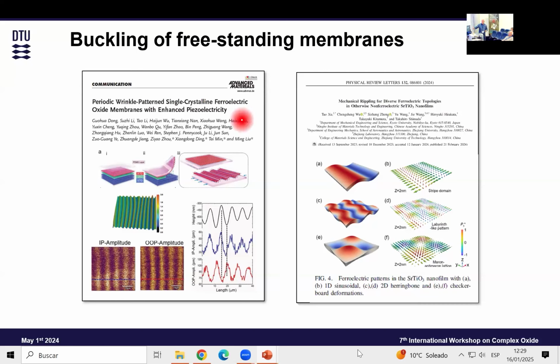So there is a response of ferroelectricity, or at least a response from the PFM, when you strain the material by forming wrinkles in the material. In another paper here, people predict some of the effects that can happen in freestanding membranes. If you have freestanding membranes with different shapes, they predict that you can induce ferroelectricity due to the flexoelectricity, basically. This is what motivates the search for ferroelectricity in the system.